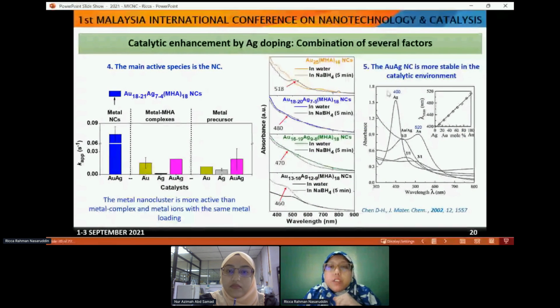And then the last reason is because the gold-silver nanocluster is more stable in the catalytic environment. Stable here means that it is stable in a small size. If you look here carefully, when we add sodium borohydride to this gold 25, after some time we have a peak at 518, and this is actually a peak of gold nanoparticle. So after some time, the gold nanocluster starts to open the ligands, does some restructuring, and becomes a bigger gold nanoparticle. But when we add the silver dopant, after some time we can still have smaller nanoparticles. That is why the activity is higher and better.